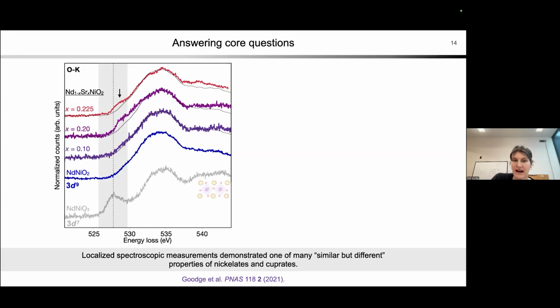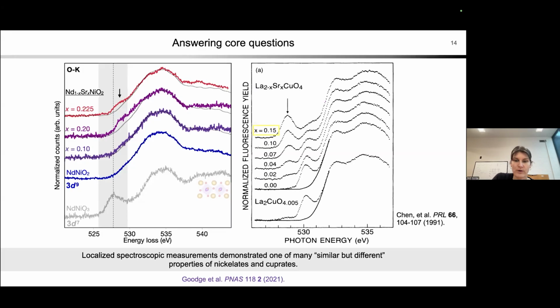And it was very hard to find because we were working off of the old cuprate literature, where you see a very similar emergent feature, again, with doping. But you can see that with the arrow in the cuprates, it's a much stronger signature than it is in the nickelates. Ultimately, what this tells us from a physics perspective is that these two materials are not exact analogs. It turns out there are some important differences between the nickelate superconductors and the cuprate superconductors as we understand them now. We're definitely still working to understand them.